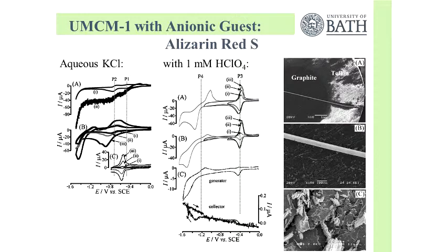If I use the material in the MOF, in the cages, again, two processes. Or if I use a little bit of acid at the beginning, I can start initially with process 3. It's the acidic process, a small signal. Then there's almost nothing. Then at much more negative potential, I see process 4. This indicates that there's a big jump in pH. Inside the pore, it's going from acidic all the way to alkaline.